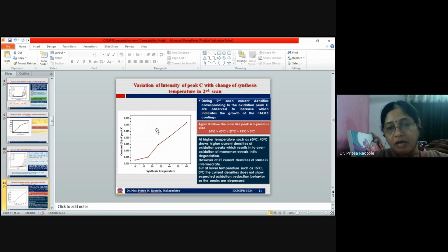Here this graph shows the variation of intensity of peak C with the change of synthesis temperature. And it again follows the order like the peak A in the previous slide. It is having the higher value for 60 degrees Celsius and lower value for 0 degrees Celsius, and all other values are in between of these.